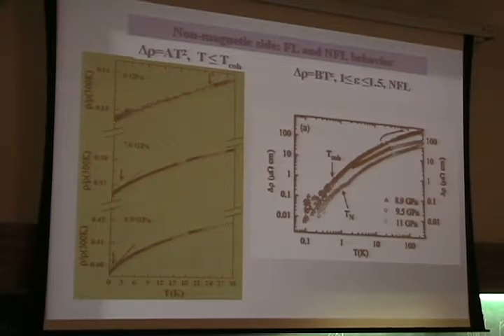And above some coherence temperature here, you also see some power law, and the resistivity can be described by this kind of power law, with this exponent between 1 and 1.5 in the case of non-Fermi liquid behavior. Okay, and within this behavior, epsilon is given by d over zeta, and for the antiferromagnetic system, zeta equal to 2 is describing a quantum critical point with a two-dimensional spin fluctuation.